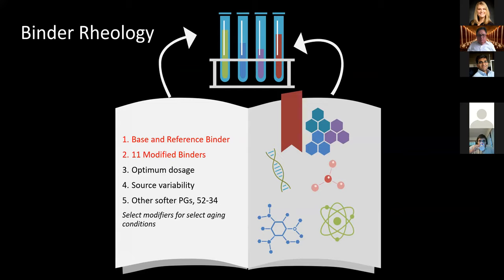The bulk of the rheology work has been performed on the base and reference binders, as well as the modified binders that were modified at the dosages recommended by the modifier suppliers. Rheological work to determine the optimal dosage, source variability, and softer PG, such as 52-34, will be continued in 2021. This project, as was mentioned earlier, has been granted an extension due to some of the lab closures in response to COVID-19.